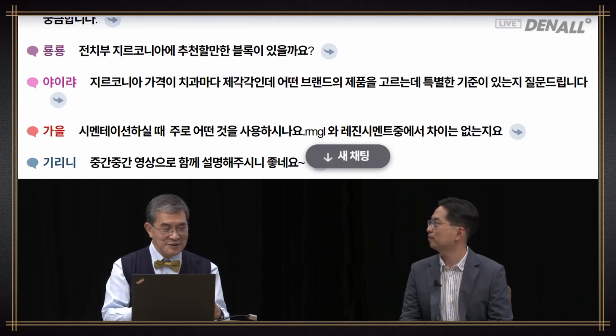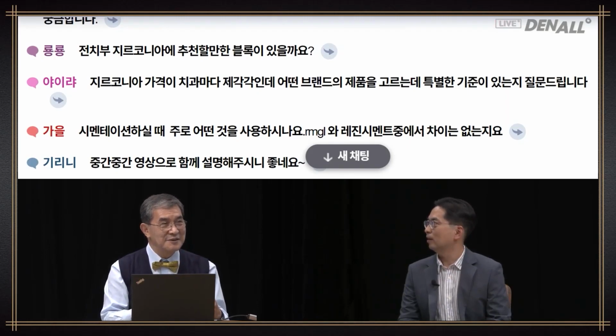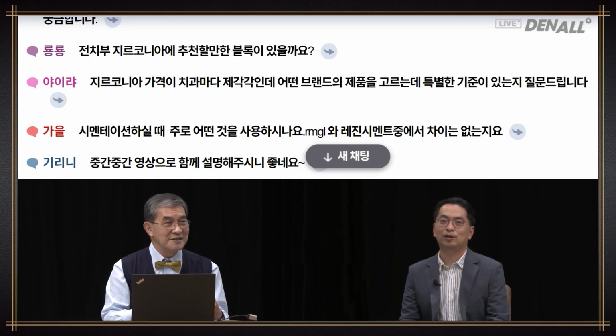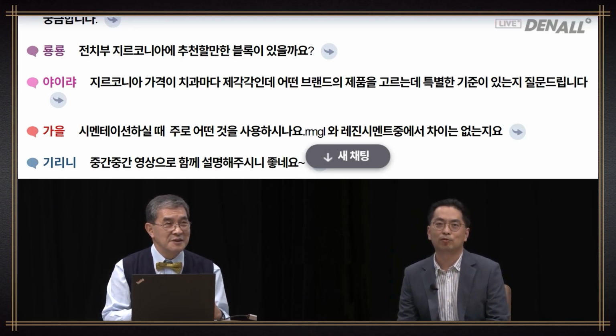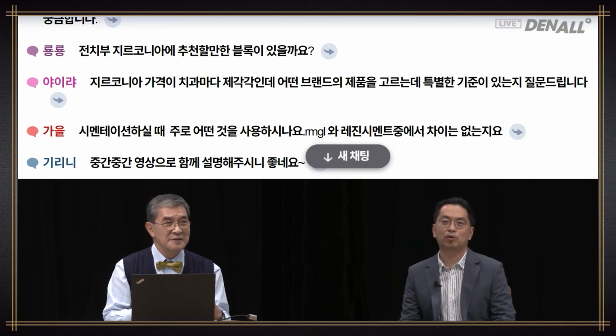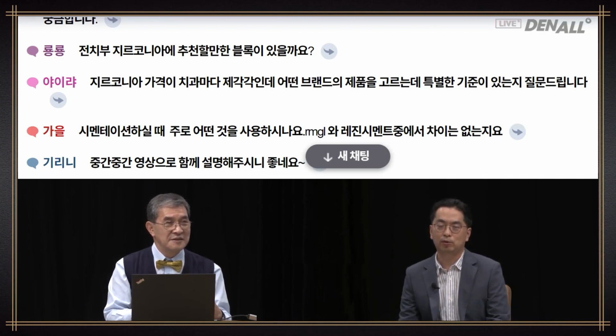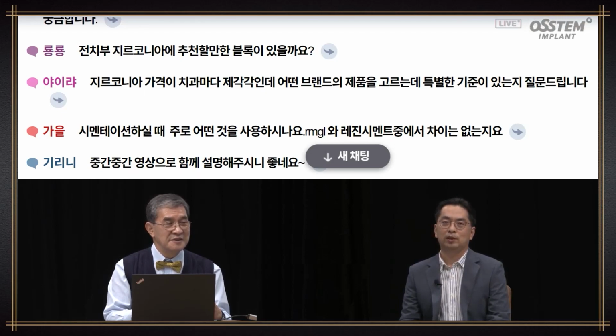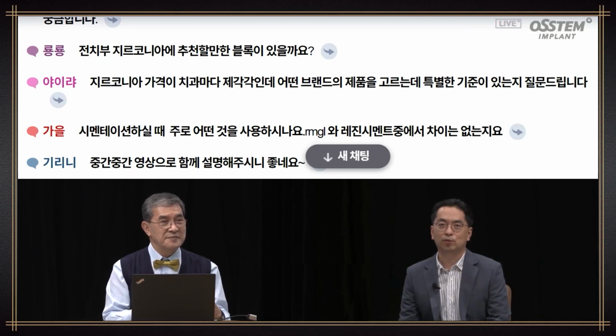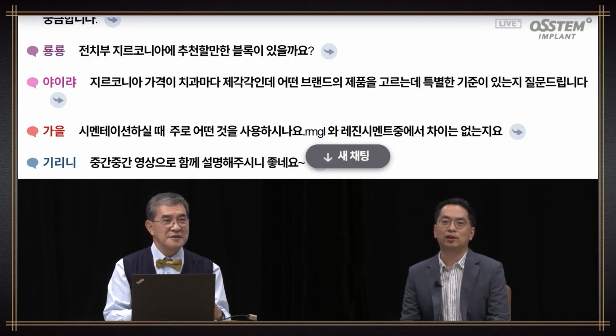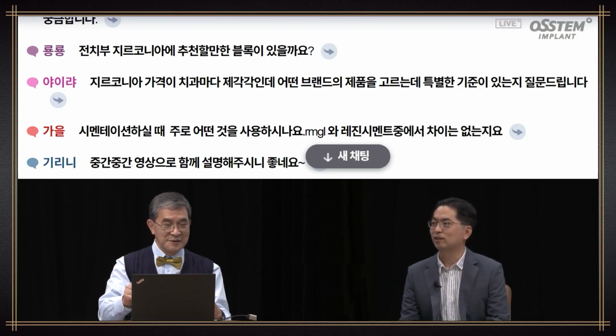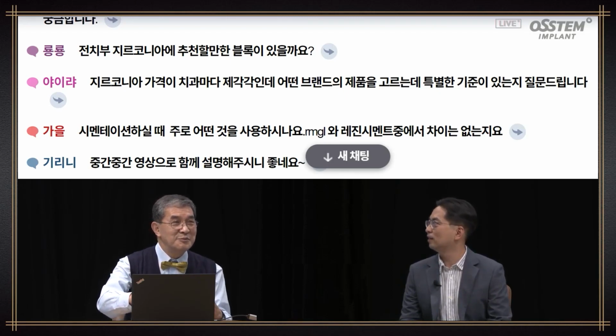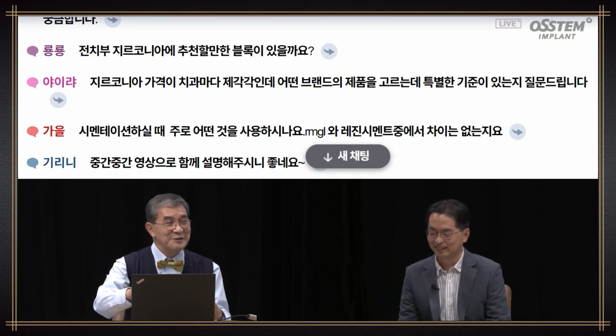Is there a block that you recommend for anterior zirconia prosthesis? It varies depending on different manufacturers. In most cases, Tosoh powder is used for the blocks. If you use a zirconia of 600 megapascal, in most cases, Z-Pex Smile of Tosoh is used or similar powder or components are used. I think you should use zirconia that is recommended for use of anterior prosthesis to provide aesthetic restorations. In live program, it's difficult to mention certain product name.